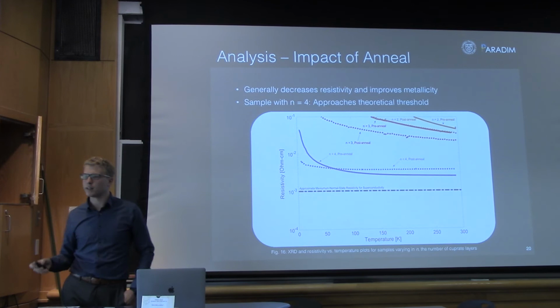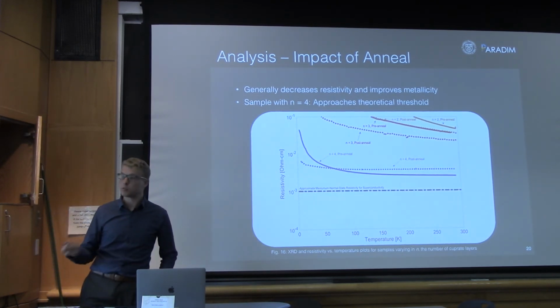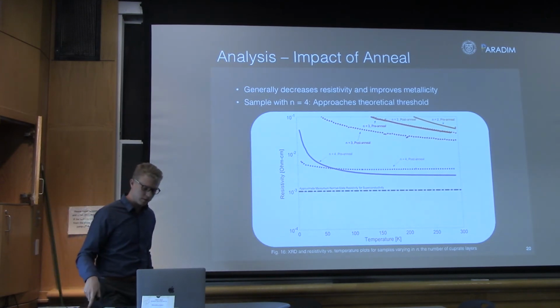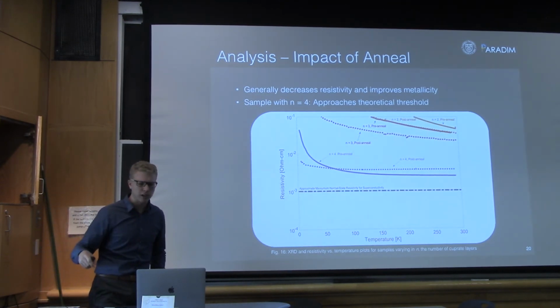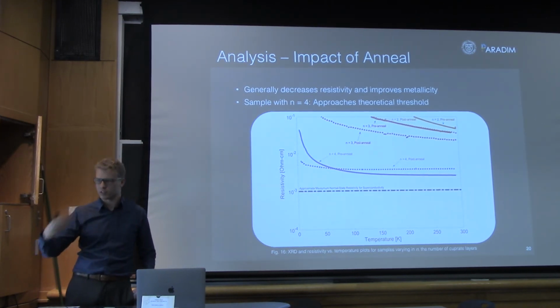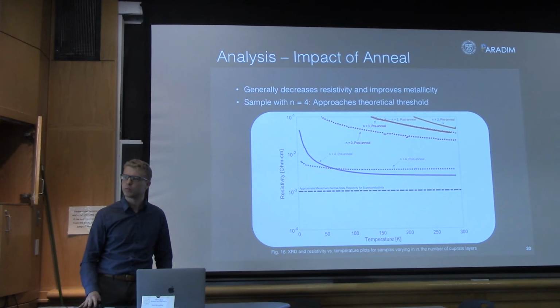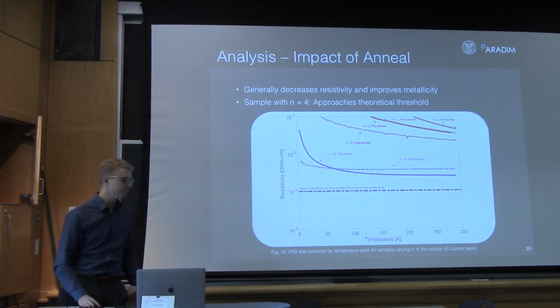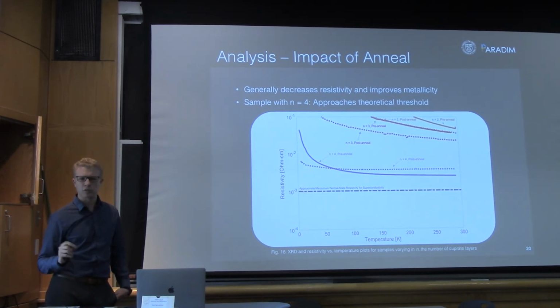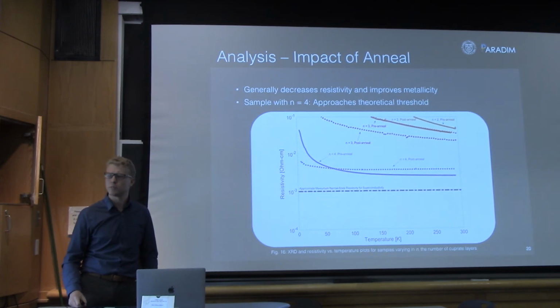It is a good question. Would it be possible that it actually got too much oxygen? It is possible, yeah. So one of the analyses, as I said, in the next steps, that optimization, the first thing I'm probably going to do is increase it to 250 degrees Celsius, 300 degrees Celsius, but also might dial back the ozone and might dial back the temperature, because it is possible that maybe too much injection just caused some sort of... We didn't see any phase change. That's one thing that's been good, and it'd be pretty noticeable because the film would cloud over. But in general, yeah, that's something to be analyzed.